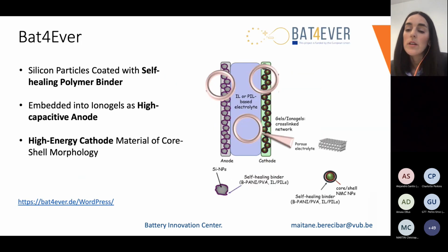And actually, this is something that we are doing today in a project that we are coordinating, called Bat4Ever. In this project, we are not only focusing on the silicon self-healing functionality, which would be this first bullet point, silicon particles coated with self-healing polymer binders, but we are also targeting other kinds of self-healing functionalities that can be applied to the anodic side or to the cathodic side, embedded into ionogels, with the high capacity of anodes and the high energy cathode materials of core shell morphology. So different kinds of possible self-healing functionalities.